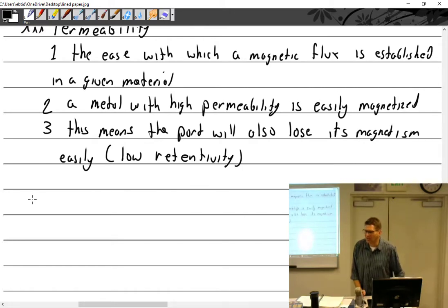Okay, so the way I do it is, you know how those wooden stands are there? Well, first of all, I do a wet continuous on the crankshaft. Then I inspect what I can in the critical areas without touching it or moving it. That gives me the opportunity, if there's anything amiss, to do another wet continuous shot. It's just really easy to do. Then once I'm satisfied of the critical areas, the best I can see, I will grab it in the areas that it's going to already touch in the stand that we have. So I'll pick it up there and put it in the stand.